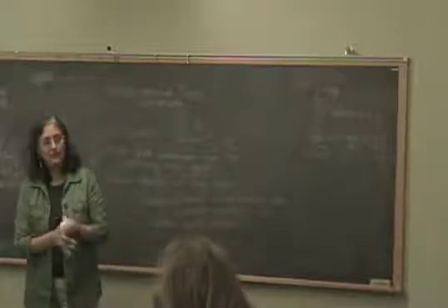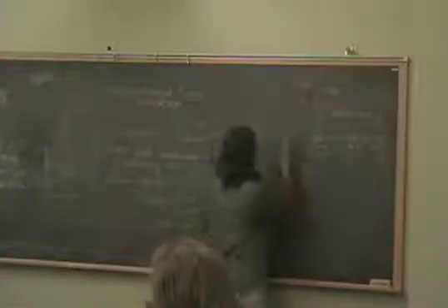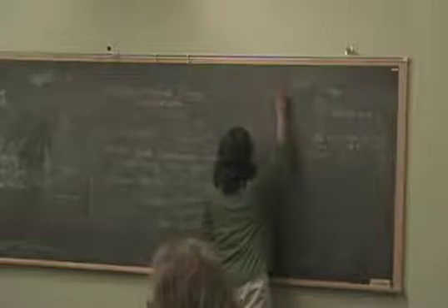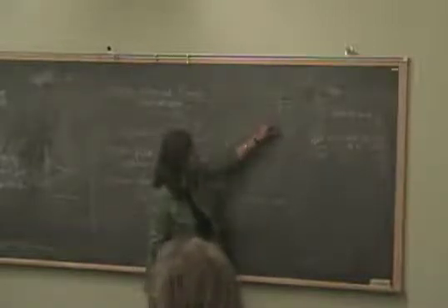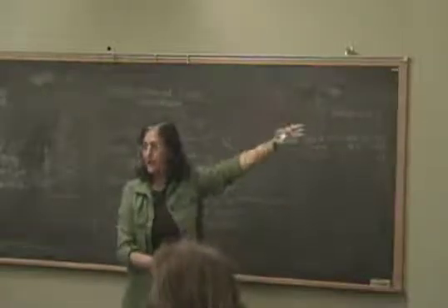If you rotated the silver particle, would you have a different plasma frequency? Yes, yes. So it's very dependent on the shape. The way to think about it is the electric field. Let's say this is my incoming wave. The electric field is going to separate out the charges, plus and minus, over this scale, but here you're going to separate it out over this elongated scale. It's what is called the depolarization effect, and that is very shape dependent. It comes in for magnetization as well. Whenever the system responds, the particular shape will change the magnetization response. So yes.